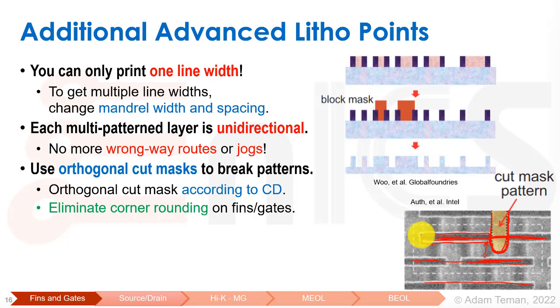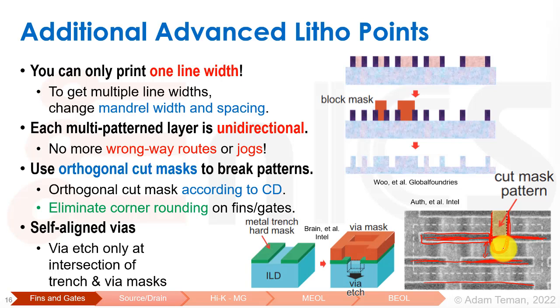So that is something that's done, and this uses standard lithography at the minimum lithographic pitch, which I said is around 80 nanometers. We do it on the polys, we do it on the fins, we do it on the low metal layers, we do it on the low diffusion layers, and so forth. So that eliminates corner rounding on fins and gates, and we have these cut masks that we'll be seeing when we discuss layout later on.